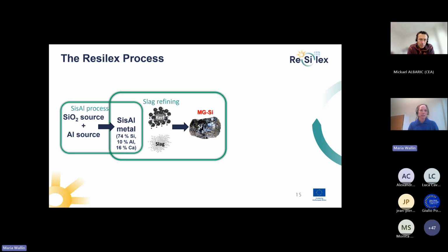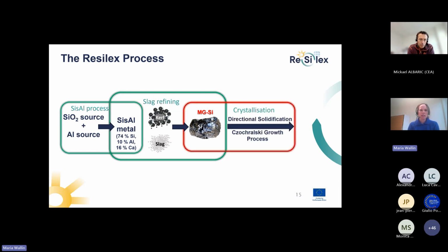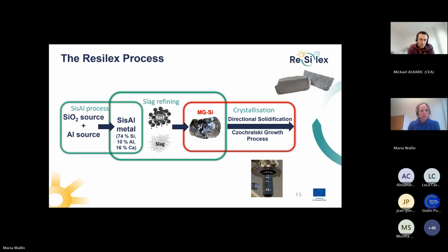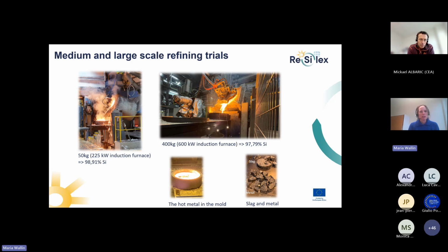We mixed the slag, this alloy, with some slag, calcium silica slag, and we produced metallurgical grade silicon that we then did a directional solidification on, or the Czochralski growth process. So we produced these 2 ingots. And here you can just see the pilot experiments that I mentioned. So we have produced both in 50 kilo scale and 400 kilo scale.